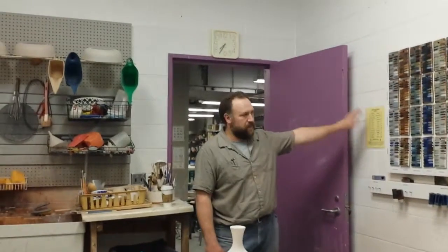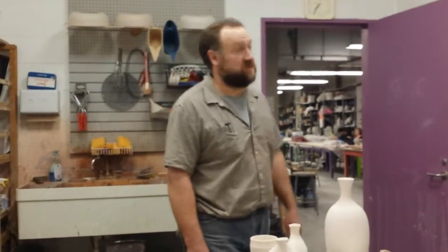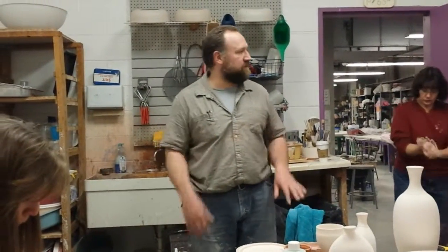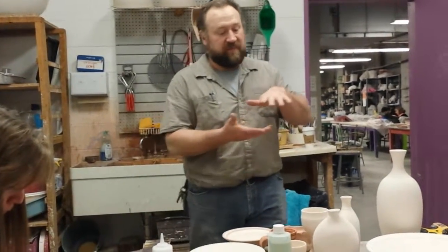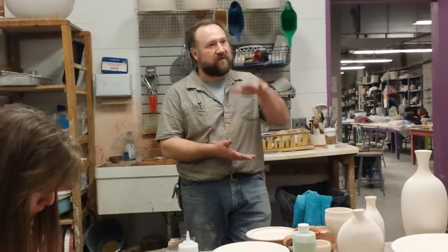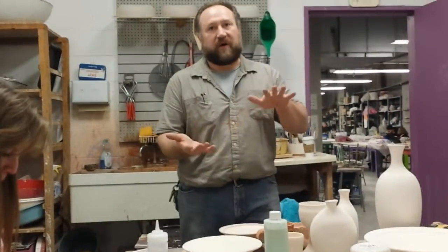The map is here. The main color is put on first and then all the little strips are on top — the background was dry when they were applied. They're fired flat so you don't get any real sense of how the glazes are going to run when gravity is more involved. My suggestion is if you're doing a two-glaze combination you've never done before, definitely keep that second coat or cover glaze on the top third of the pot until you gain confidence in how much it's going to run. Then you can start moving your way down, and if you want, cover the whole pot with a second glaze.